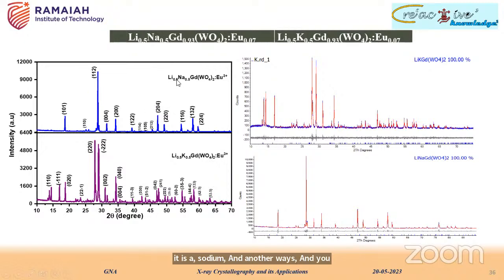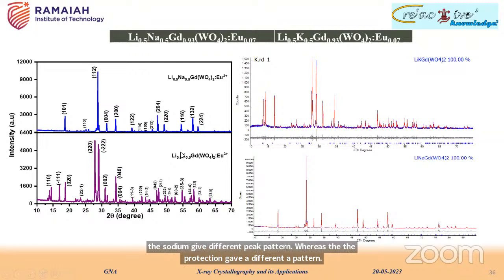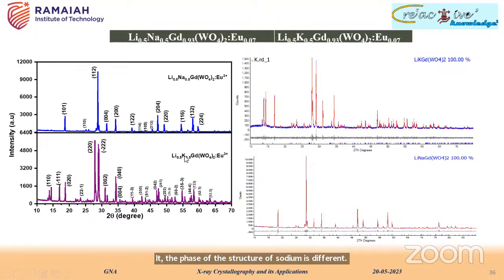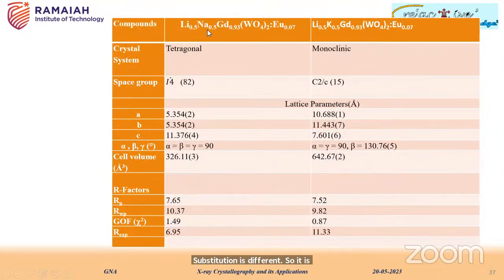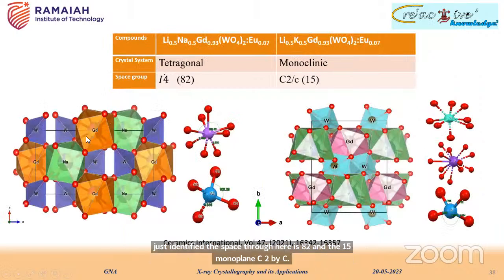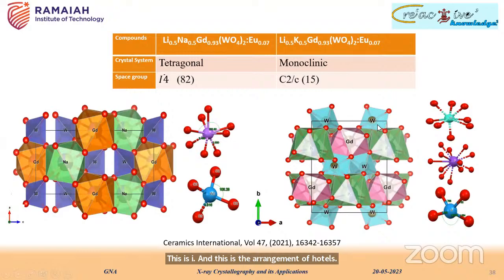And you see that we have just modified it, we replaced the sodium with potassium. But the sodium gave one peak pattern, whereas the potassium gave a different pattern. It clearly suggests that the structure of sodium substitution is different and the structure of potassium substitution is different. So one is tetragonal, sodium crystallized in tetragonal phase, whereas potassium crystallized in monoclinic phase. And we have just identified the space group here. It is C2/c, monoclinic, and this is the I4 bar. And this is the arrangement of atoms, gadolinium, tetragonal and monoclinic structure.